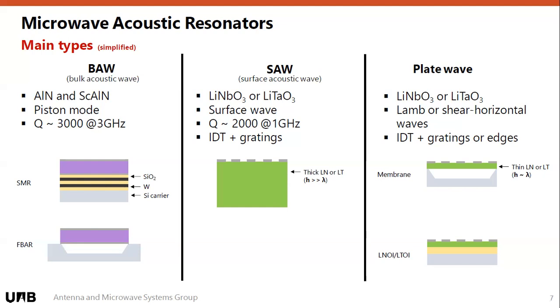Regarding plate waves, you have mainly two types of resonators. You have a membrane approach, in which below your thin layer of piezoelectric material, you have air, so you can get isolated from the substrate. Or what we're going to do, it's called LNOI or LTOI, depending on whether you use lithium niobate or lithium tantalate on insulator. So it's your piezoelectric material put on top of an isolating layer that has some specific mechanical characteristics, so that it isolates the wave from the substrate.